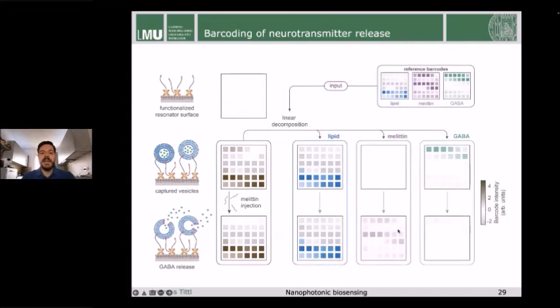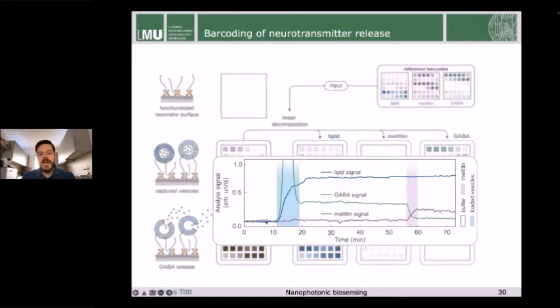I'm showing you here just the final analysis where we could differentiate all the different biomolecules in the system. So the lipids, which stay mostly the same, even though you are making small perforations in the vesicles, the melittin that in the beginning is of course not present, but then gets attached to these vesicles, and the release of the neurotransmitter, which is present with a high signal in this first step and then gets released. And by recording this over time, you can actually get a real-time and detailed picture of the neurotransmitter release process in the system.